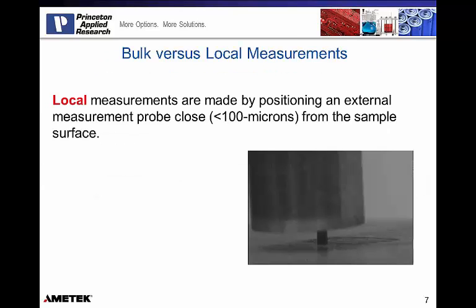So let's contrast that to a localized measurement. Localized measurements are made by positioning an external measurement probe close to the sample surface. So these are non-contact measurements. When we say close for an SECM, we're looking for about 2 to 4 probe diameters away from the sample surface. So it's non-contact, but in an example of a 25 micron probe, you want to be between 50 and 100 microns away from the sample surface. That's going to be roughly the diameter of a human hair away from the sample surface.